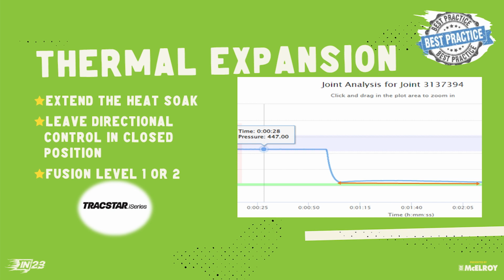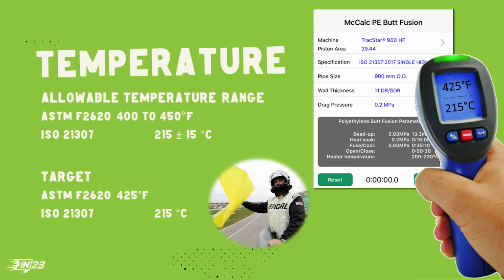Let's talk a little bit about temperatures. Alan, what temperature are we looking for? 400, 450. So we usually shoot right down the middle, 425, 215 in the case of ISO. Best practice for heavy wall, we're going to want to go up to the higher end of that temperature range.